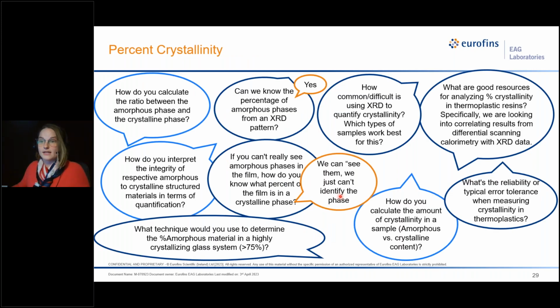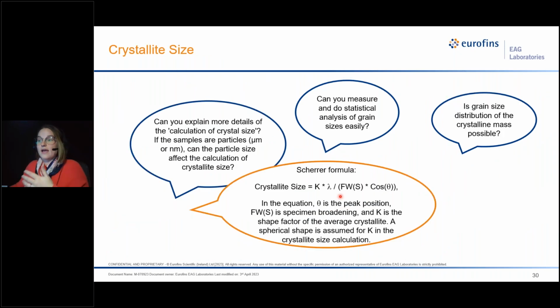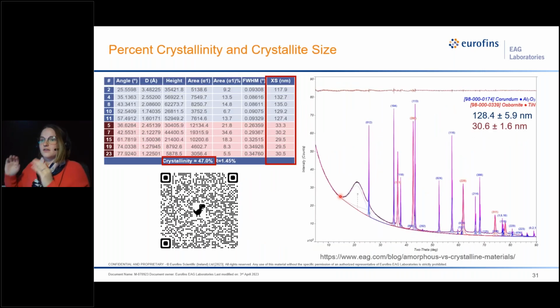Next is percent crystallinity. How much of that is amorphous and how much is crystalline? Now, when you're calculating this ratio, it's just area under the curve. So we have to know essentially how broad the peak is. And similarly with profile fitting, which is what we do for percent crystallinity, it's also how we're going to calculate crystallite size, which is the second math formula that you're going to see today, and the last is the Scherrer formula. That's the formula we use to calculate crystallite size. So this is percent crystallinity and crystallite size.